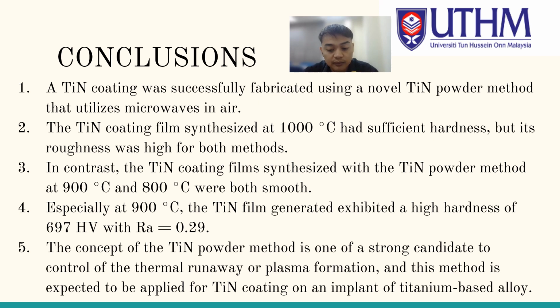The concept of the TiN powder is a strong candidate to control thermal runaway or plasma formation, and this method is expected to be applied for TiN coating on implants of titanium-based alloy.